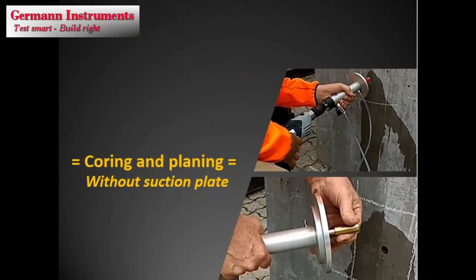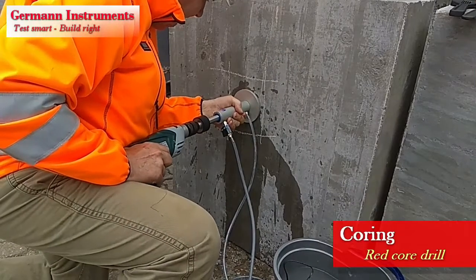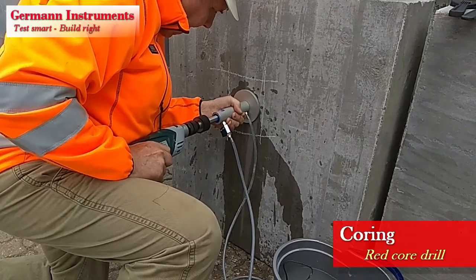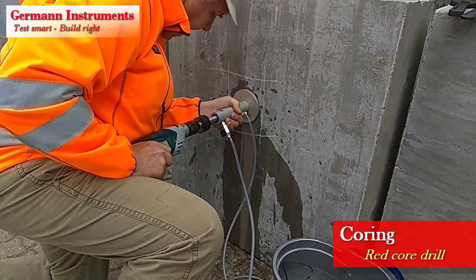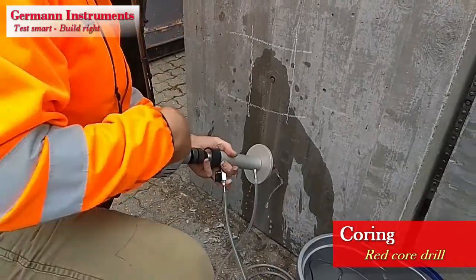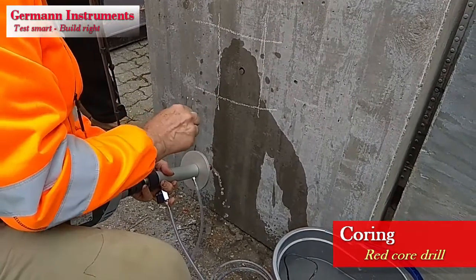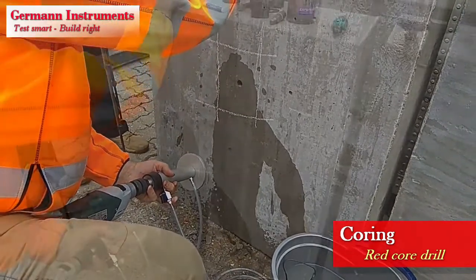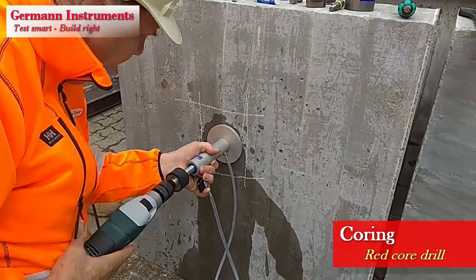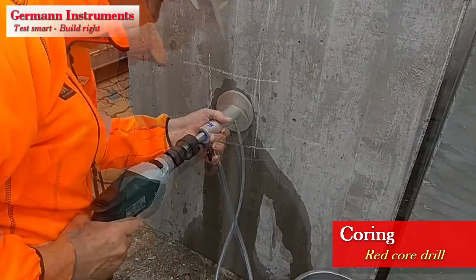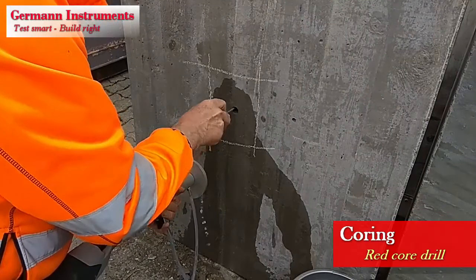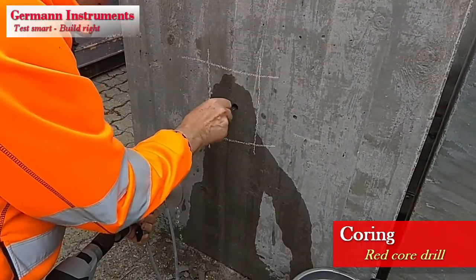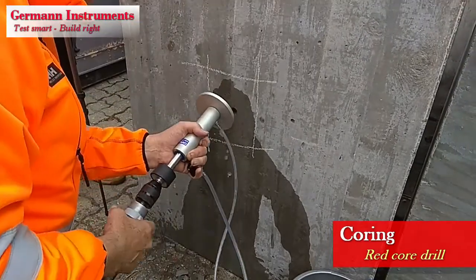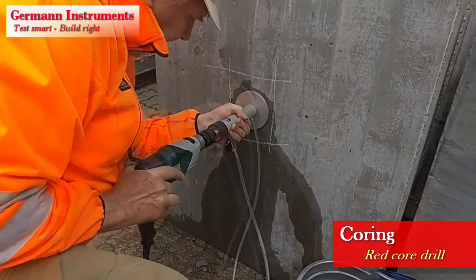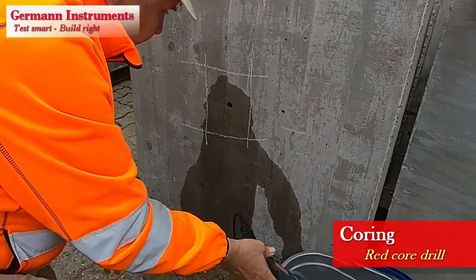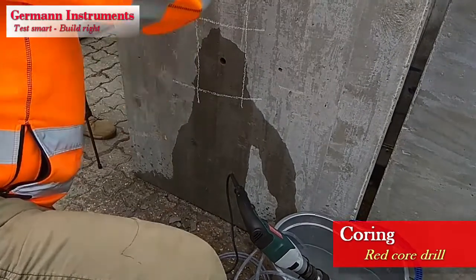Without the use of the vacuum plate, the 3 initial steps are done as follows. Attach the red diamond coring bit to the coring unit as well as the water hoses similarly as illustrated previously. Core first to half depth, remove the core in pieces and continue coring to full depth. Break the remaining core and remove it by the tweezer.